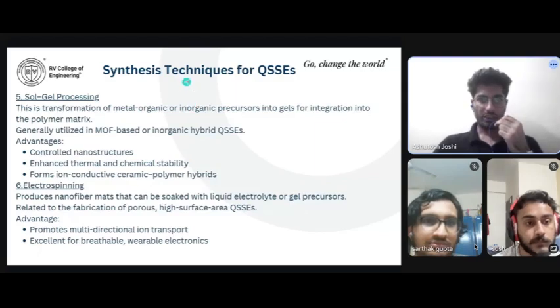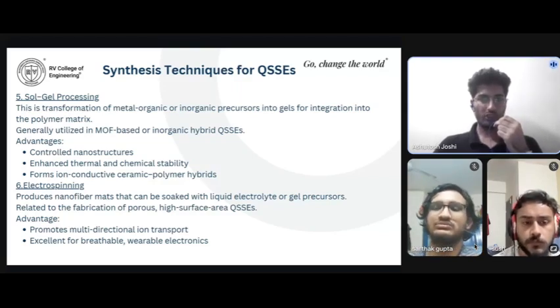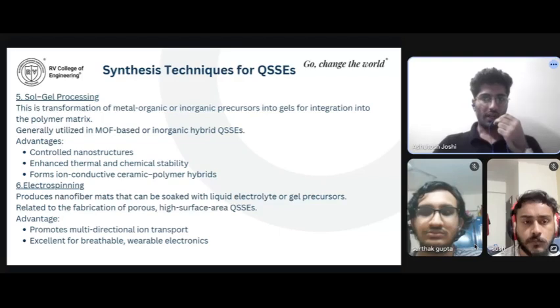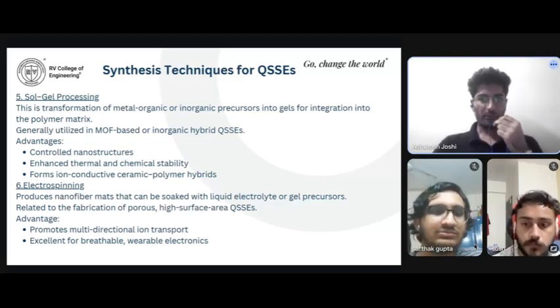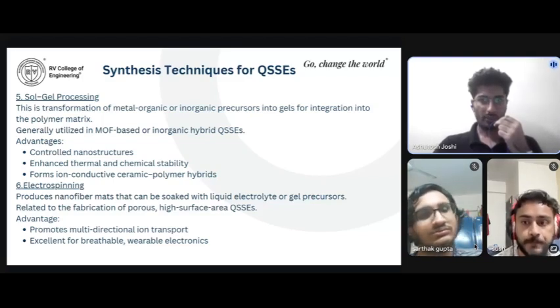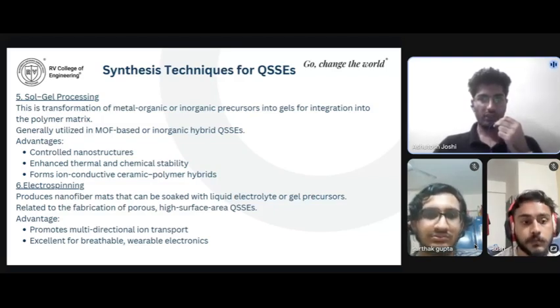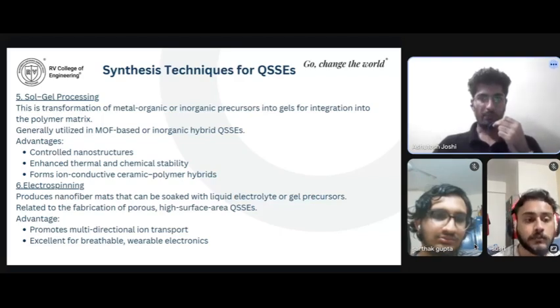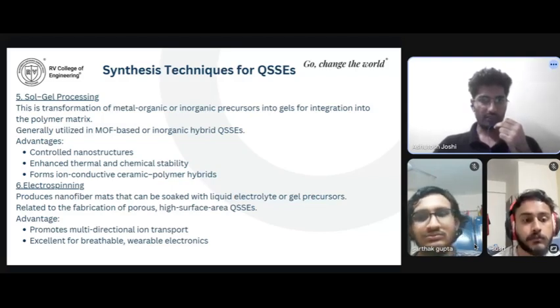Now, the fifth synthetic technique is the sol-gel process. It is a chemical method that helps introduce a ceramic or inorganic phase into the polymer matrix for improved QSSE performance. This method involves hydrolysis and condensation of metal-organic precursors like alkoxides to form a stable gel. Its applications are in creating MOF-based, SiO2 and TiO2 embedded QSSEs. Its benefits include enabling nanostructural control, ideal for tuning ion pathways, offering enhanced thermal and chemical stability, and promoting uniform ion conductivity, especially in mixed-ion batteries. Next.